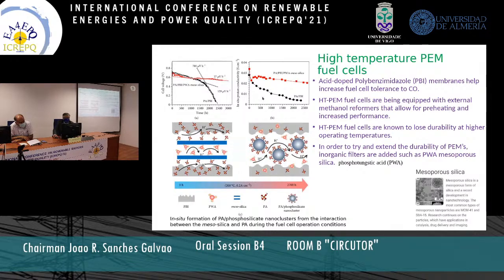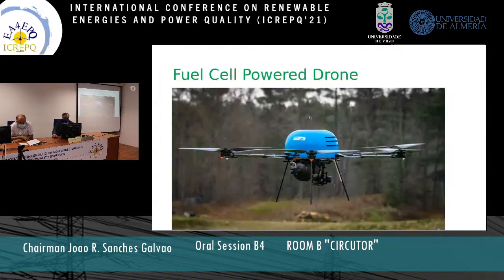And on this curve on the right side, we're looking at proton conductivity of the membrane as a function of number of hours of operation. It is shown that the conductivity drops fairly rapidly with phosphoric acid-based membranes, but once the mesosilica nanomaterial is added to the membrane, you can see that the conductivity does not drop very much with the number of hours of operation.